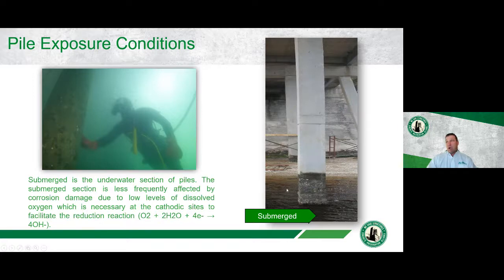So the first area that I'm going to talk about is this submerged section down here. So this is everything that is constantly submerged in the water. And this section here within the water, one thing to note is that there's not a lot of oxygen available. There's a limited amount of oxygen that's dissolved in the water. But for the most part, there's not a huge amount of corrosion that's occurring down here. It's not extremely aggressive. It can occur down here, but it becomes much, much more aggressive once you get up into this tidal zone.